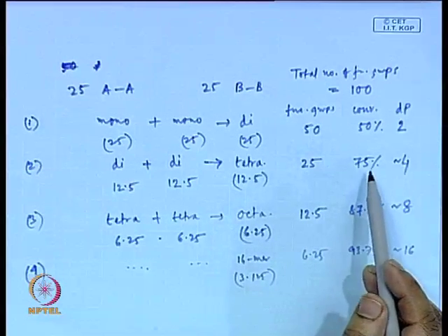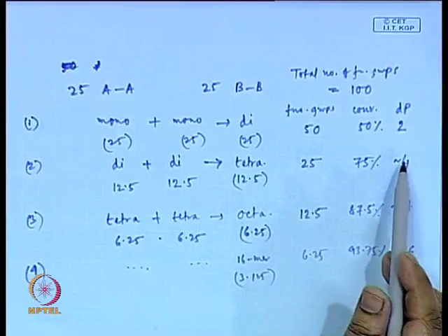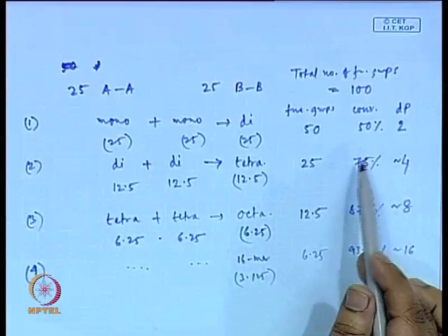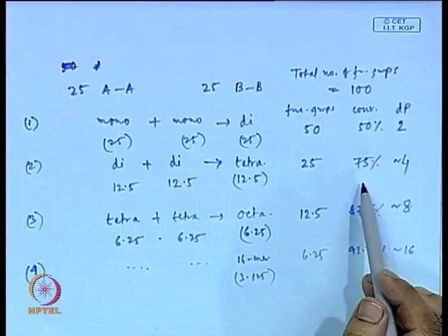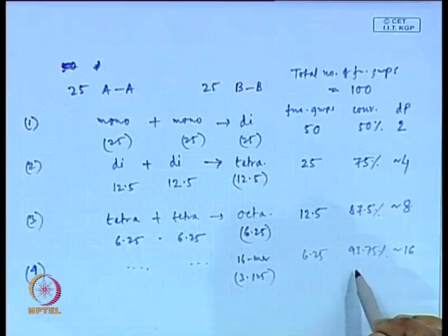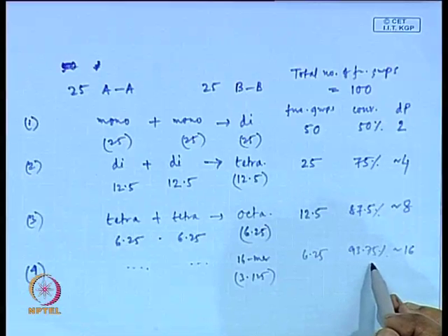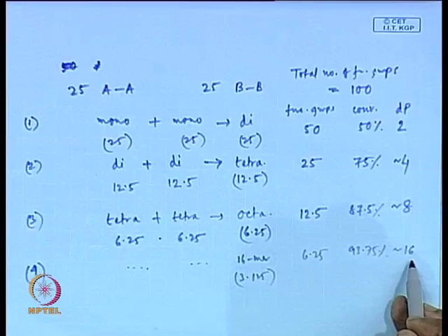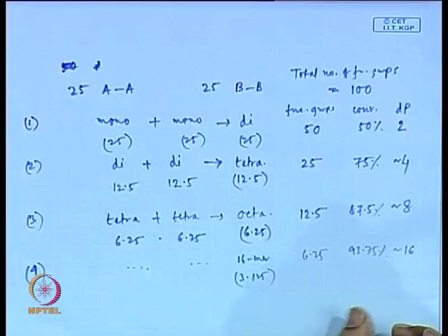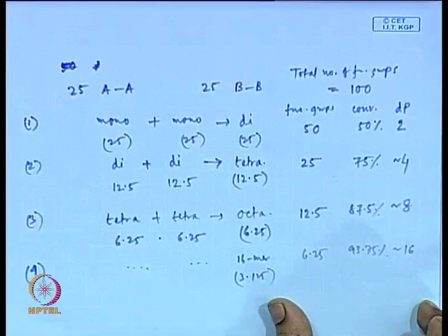So, even at very low dP, you have a high amount of conversion. This emphasizes that, for example, at say 94% conversion, you have only 16 dP, which is not a polymer yet. Okay, it is still an oligomer.